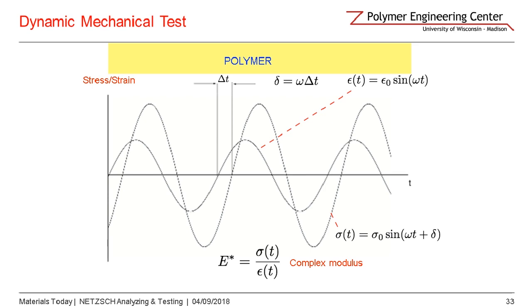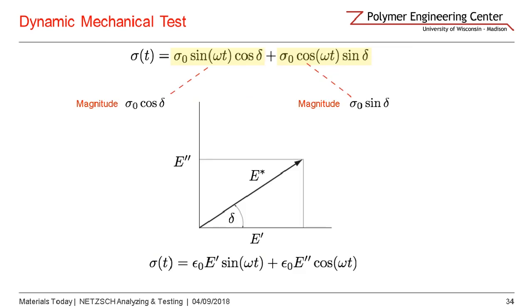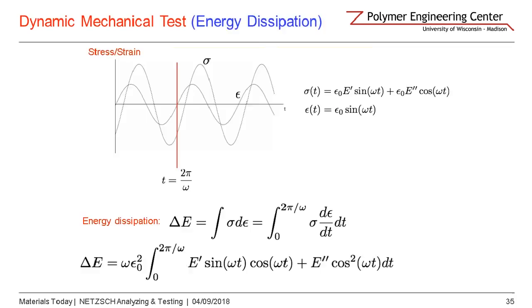That angle delta is the lag of the stress response to the strain input. The DMA equipment from NETZSCH does all those calculations — giving you the complex modulus. The portion proportional to cosine delta is the storage modulus, and the portion proportional to sine delta is the loss modulus. The cosine is related to the elastic portion — what you recover when the ball bounces up. E double prime, the loss modulus, is what you lose when the ball bounces up.